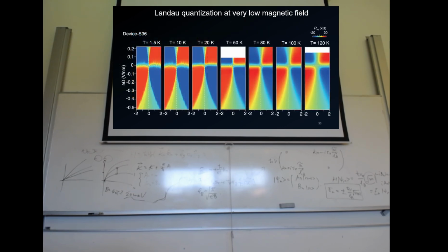This is basically how it looks at a very low temperature. If you change the temperature from 1.5 Kelvin to 120 Kelvin, the whole behavior is preserved at very high temperature. So that means the antiferromagnetic ground state, which has a Néel temperature of 13 Kelvin, somewhere here, is not a factor which determines the observation. So it is not related to the magnetism of the substrate here.